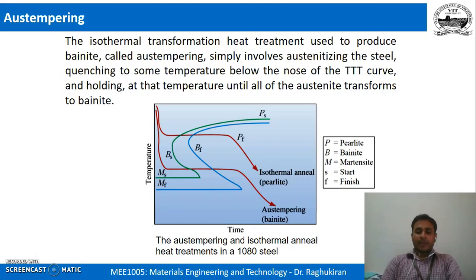So bainite, you already know, is again a combination of ferrite and cementite, but ferrite with a lot of dislocations. As I already mentioned, this ferrite has hardness more than what you see in the ferrite in perlite. In bainite, whatever ferrite you have is typically harder, because of the large number of dislocations that are induced. How can you get bainite? You see this TTT diagram.